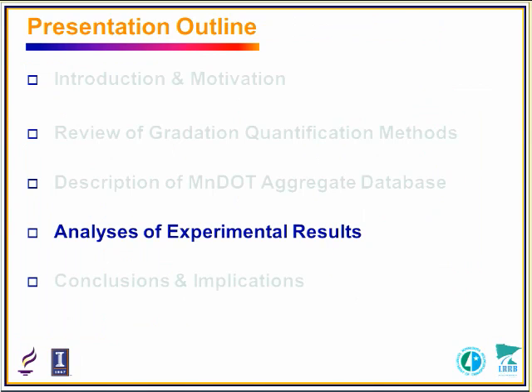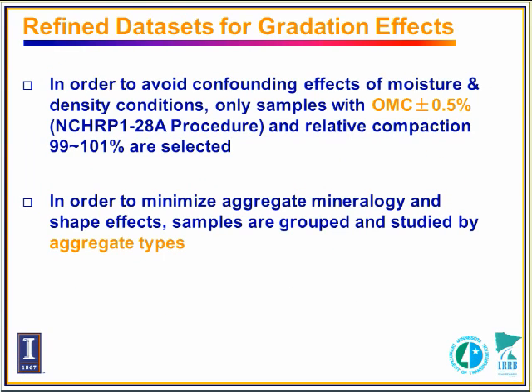So after that, I want to go to the analysis results. It needs to be emphasized that because those materials were tested at different labs and collected from different project sites, there may be some variation inside. In order to minimize the variations, we eliminated some data sets. For example, we stuck to the data sets which have optimum moisture content fluctuation around 0.5%, and the relative compaction level within 99 to 101%. Some data sets did not follow this requirement, so we didn't use them, just to make sure that the samples we studied are approximately at the optimum condition.